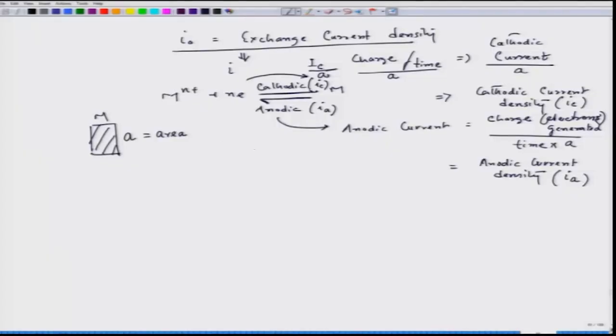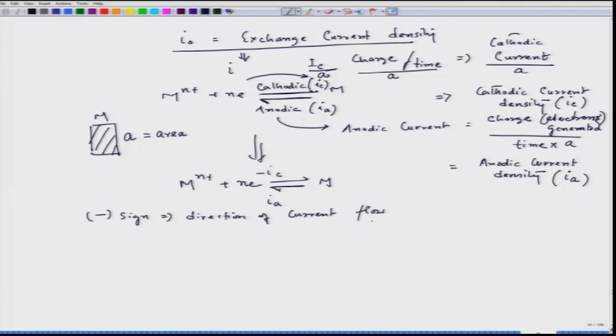Now, see, these reactions, M going to M^n+ plus n e^-, this reaction is taking place simultaneously, and then they will reach equilibrium. So, IC, IA. Now, if I consider this particular direction, the current density to be IA, then the reverse direction, which is the cathodic reaction rate, we shall mention in the form of minus IC. Now, this negative sign indicates direction only of current flow. It does not tell that the current density is actually negative. Magnitude is positive, but negative means it is flowing opposite to the anodic current.